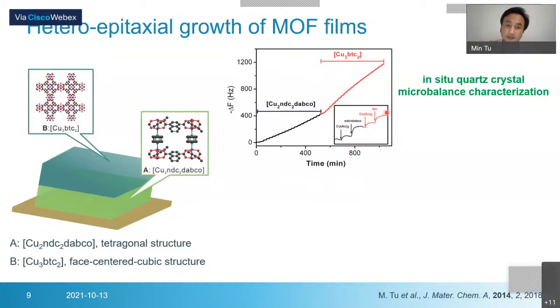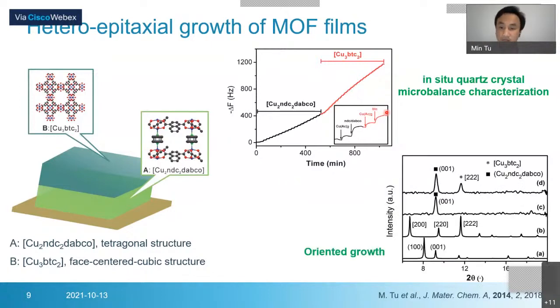Then to connect with the bottom layer, if you look at the out-of-plane XRD, you can see the bottom layer grows in the 001 orientation. Then the copper BTC also shows oriented growth, in the 111 orientation. So this kind of technique is kind of straightforward. It's simple, and it has its advantages. But the only problem with this kind of method is working with big areas. Typically we work with 1 inch or 2 inch substrates, and then we can get a kind of homogeneous film.